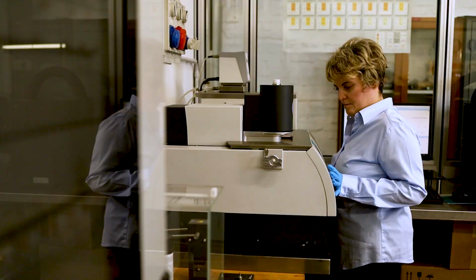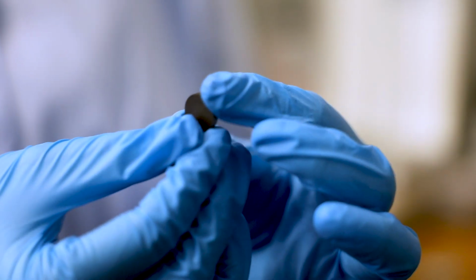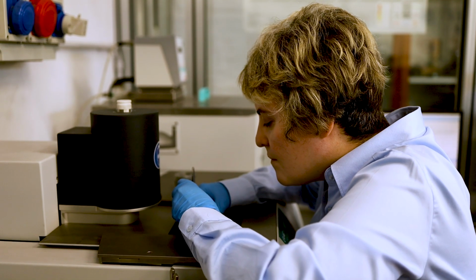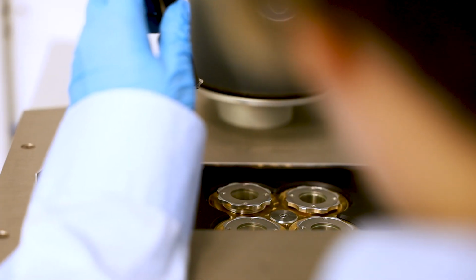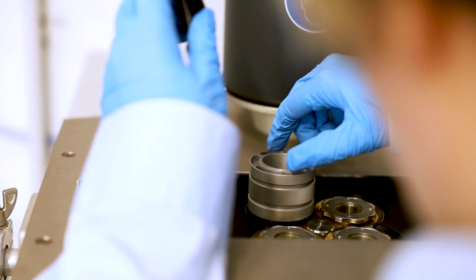To produce a radiant tube, you need high thermomechanical properties and very specific thermophysical properties. In particular, because these tubes become hot and have to transfer heat. We can characterize CMC samples with different densification levels. In particular, what we are going to do with this apparatus is to determine the thermal diffusivity of the sample. That is a fundamental parameter that explains how fast the heat diffuses through the sample. Thanks to these results, we can provide reliable input to the modeling activities. The modeling activities will be aimed at describing the behavior of the radiant tube in a real working environment.